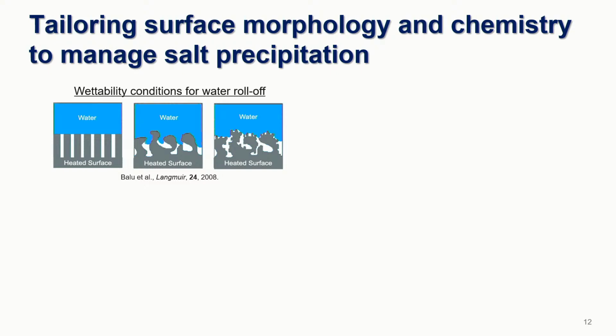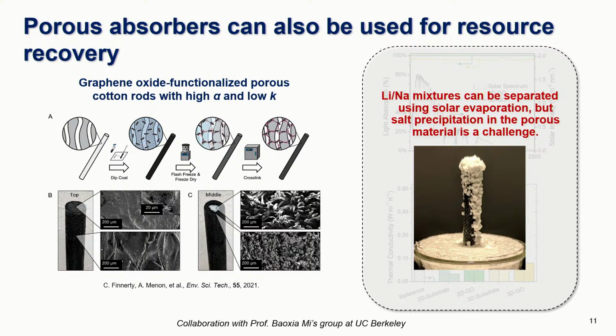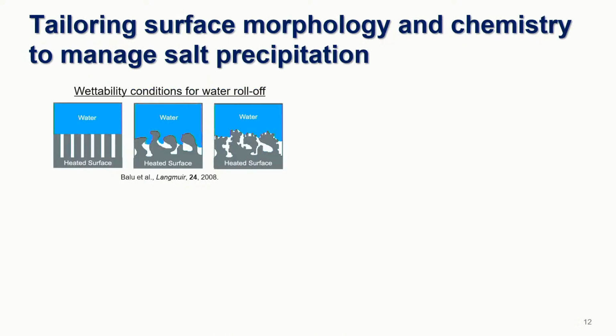So moving on, we're also looking at how do we really handle these situations when you have a lot of salts that precipitate out. Over time, you're basically blocking all of those pores, and you're also losing your solar absorption because you're now covered with these white salts, right? And so we're looking at how can we modify or tune the salt precipitation on different surfaces. And so specifically what we've seen in the literature is, you can create these types of regular microstructures on your substrate in order to create hydrophobic or superhydrophobic surfaces. And then if you add hierarchical roughness, so now you're adding nanoscale as well as microscale roughness, then you could get not just superhydrophobic behavior, which means that your water really does not wet the surface, but you also get the water to roll off the surface very rapidly, so it doesn't adhere to the surface.